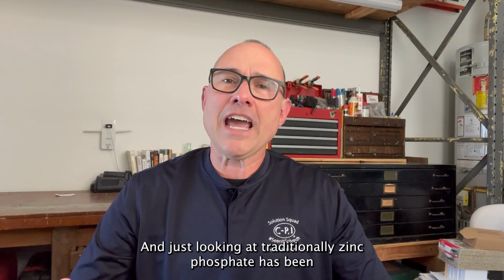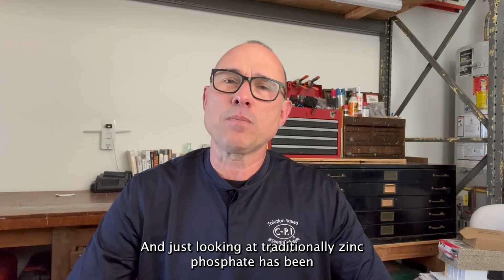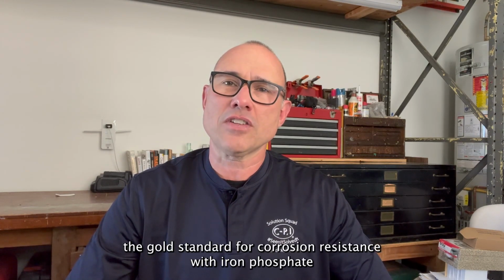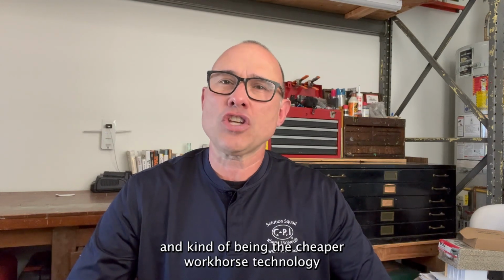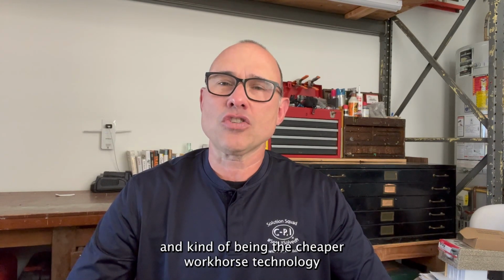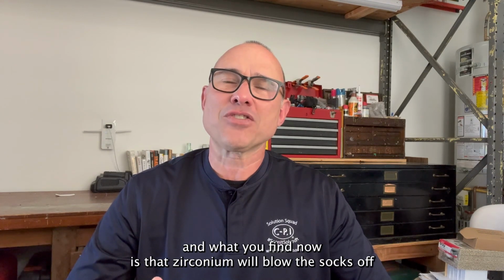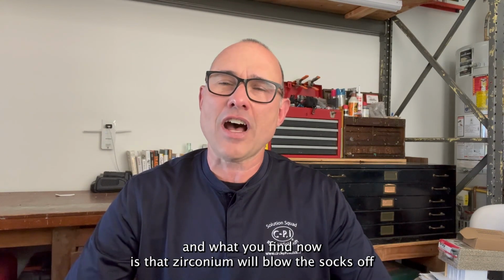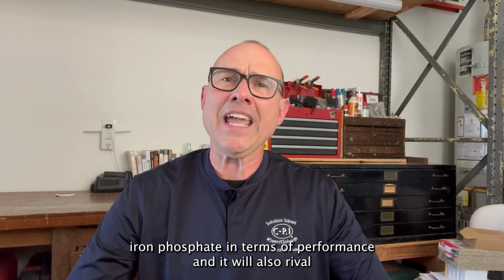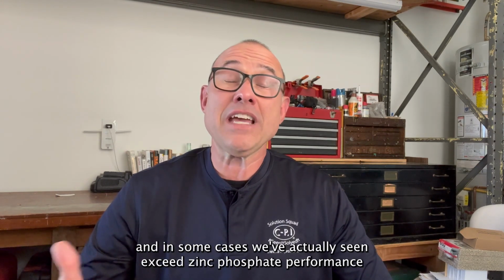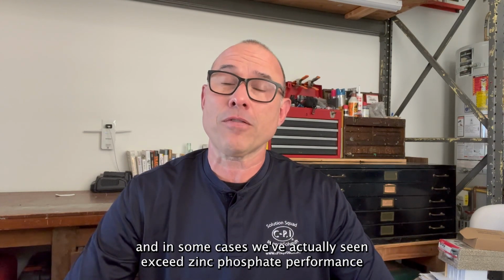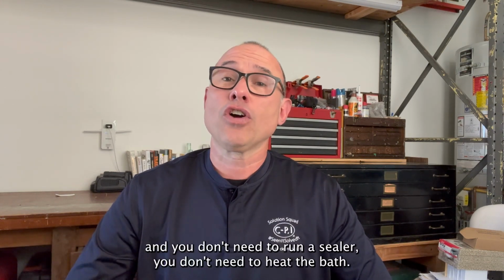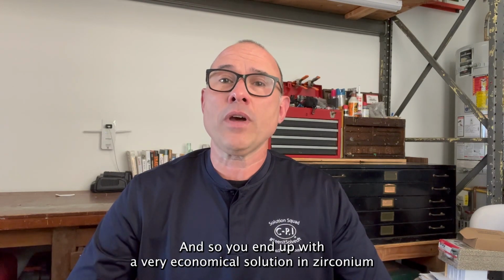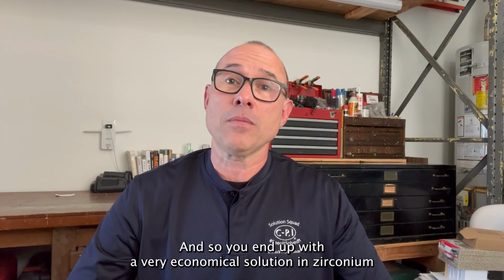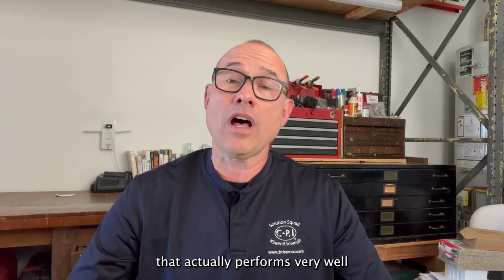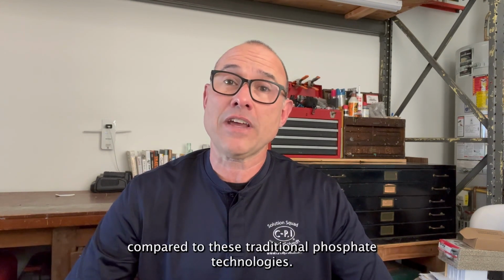And just looking at it, traditionally, zinc phosphate has been the gold standard for corrosion resistance, with iron phosphate being the cheaper workhorse technology. And what you find now is that zirconium will blow the socks off iron phosphate in terms of performance, and it will also rival, and in some cases we've actually seen exceed, zinc phosphate performance. And you don't need to run a sealer, you don't need to heat the bath, and so you end up with a very economical solution in zirconium that actually performs very well compared to these traditional phosphate technologies.